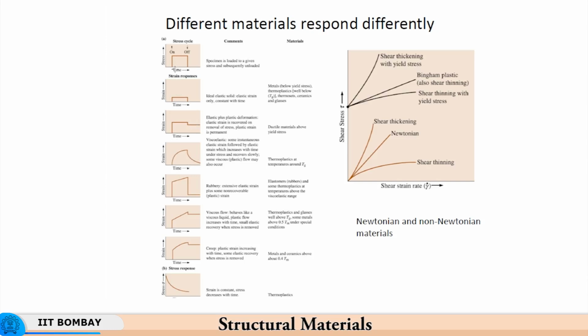For the same variation in the stress, now you see that there is a non-linear variation in the strain, because there is a phase lag between the development of strain and the rise in stress. The rise in stress is very sharp, very rapid. For an elastic solid it was equally rapid, for an elastoplastic solid also it was equally rapid, but now with a viscoelastic solid, because of viscous effects there is a phase lag between the stress and the strain. So, the stress rises instantaneously as shown here, but the strain does not rise instantaneously to its maximum value. And then when the load comes down, it also does not relax instantaneously, and so this phase lag is introduced because of viscous effects.